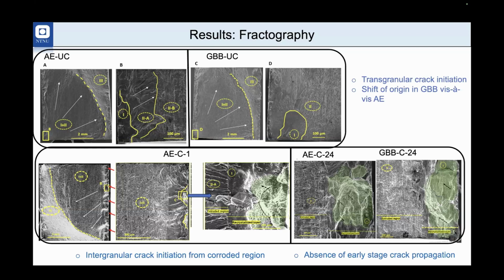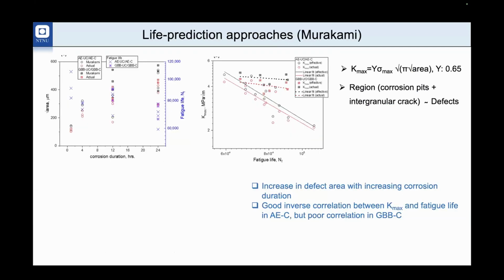So not only did it curtail the crack initiation phase, but it probably also curtailed a portion of the early stage crack propagation. So that's why, compared to 1 hour, if you go to 24 hours, it's because of the loss in the crack propagation phase, the early stage crack propagation phase.